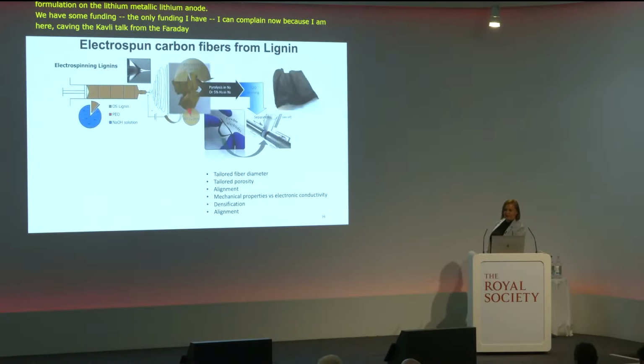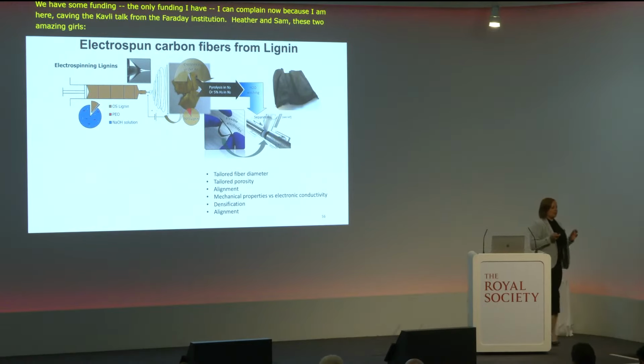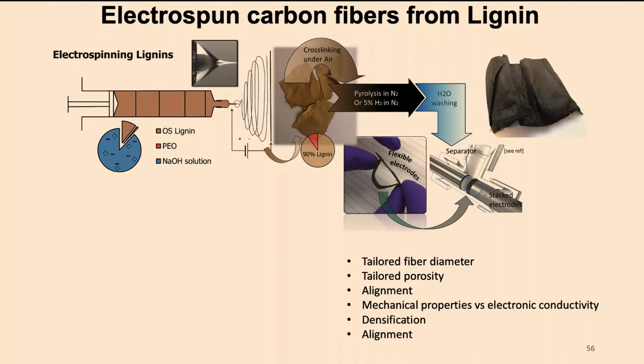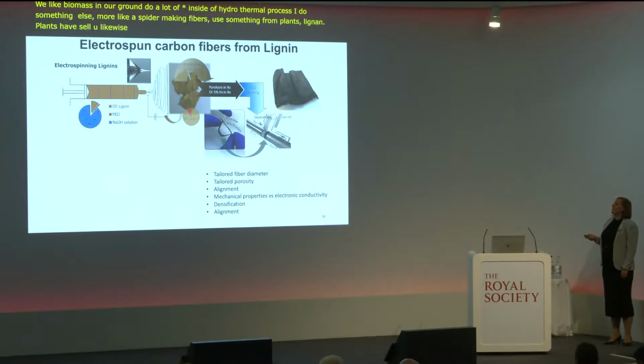And what they're trying to do is to make a self-standing lithium-sulfur battery. So we like biomass in our group, and we do all our carbon materials from biomass. Here, instead of using this hydrothermal process, I use something else that is more like a spider making fibers, and we use something from plants, which is called lignin. So plants have cellulose and lignin. Jason knows that. And hemicellulose. So the lignin is the one that gives structure to the plants.